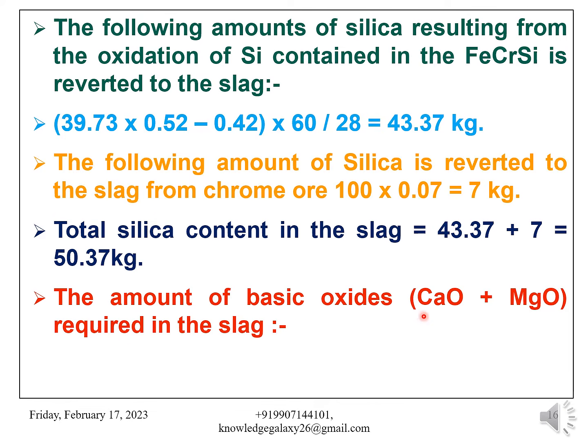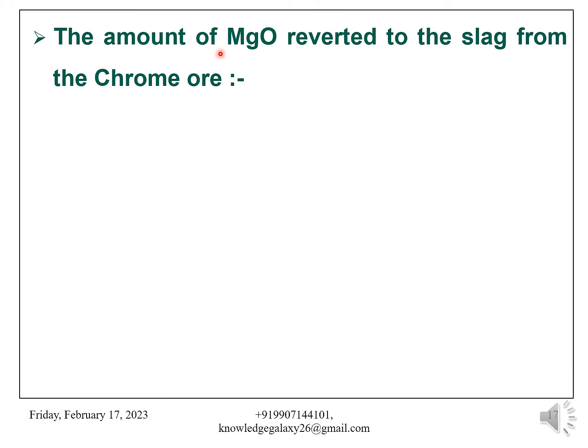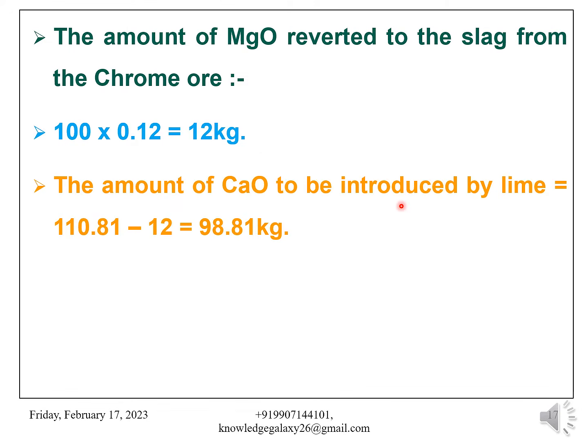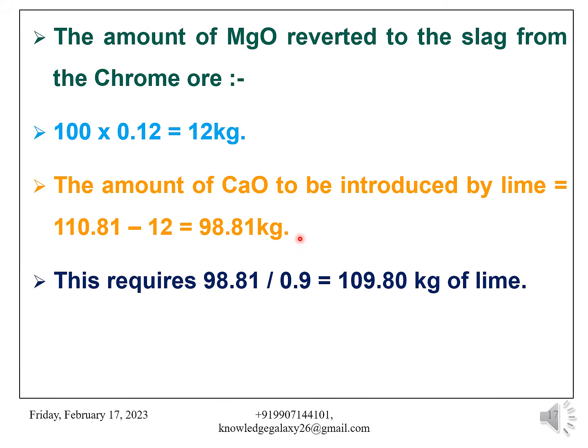The amount of basic oxides CaO plus MgO required in the slag is calculated as 50.37 × 2.2 = 110.81 kg. The amount of MgO reverted to the slag from the chrome ore is calculated as 100 × 0.12 = 12 kg. The amount of CaO to be introduced by lime is 110.81 − 12 = 98.81 kg. So this requires 98.81 / 0.9 = 109.80 kg of lime.